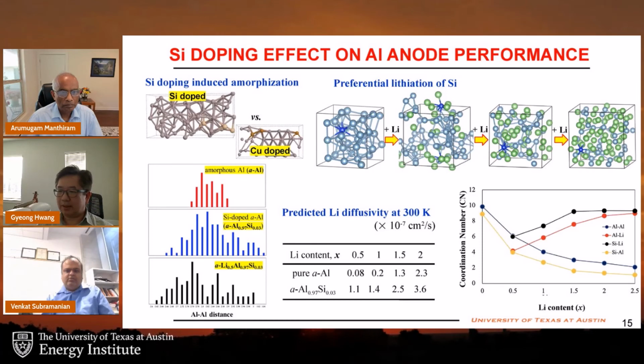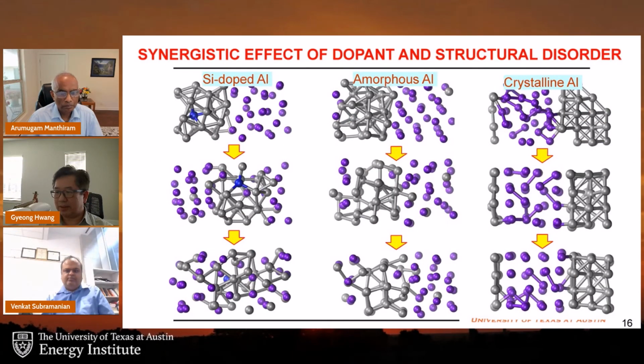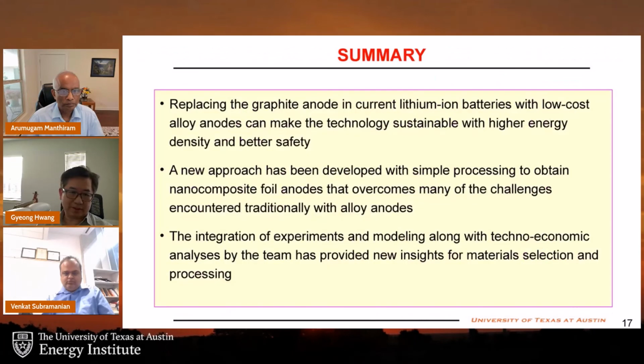The next slide shows the synergistic effect of dopant and the structural disorder on the lithiation performance of the aluminum-based anode. As shown in the right figures, in the crystalline structure, the aluminum is hardly lithiated. But we have found that the lithiation performance is significantly enhanced when the aluminum structure is highly disordered, and also silicon dopants are present in the aluminum matrix. So our results clearly support the experimental observation of improved performance of aluminum foil anode with a small amount of silicon incorporated, like what Ram presented. Okay, this is it for my presentation.